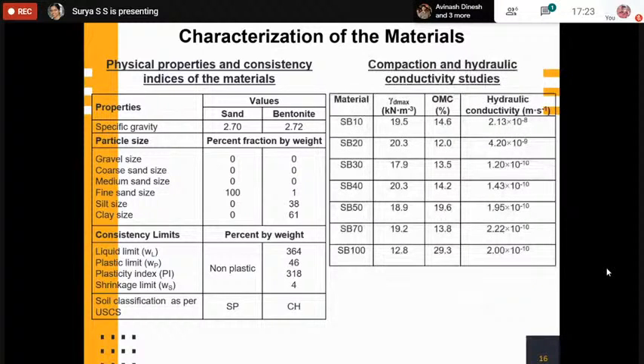And this is the compaction result. Since, as I told, we'll be mixing bentonite and sand, I have to try different weight proportions of sand and bentonite. So accordingly, I have named like SB10 means sand bentonite mixture with 10% of bentonite content according to the weight. For different sand bentonite mixtures, I have conducted compaction test. I did both standard proctor as well as miniature compaction testing, and I could observe that both the results are matching. And also, I have conducted hydraulic conductivity testing.